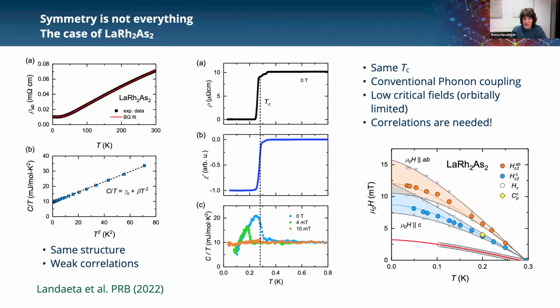What we know from our studies is that the structure is not enough to get the two superconducting phases. So what we did is we studied this sister compound, LaRh2As2. So it has no f electrons and is a weakly correlated material. So the gamma is only 10 millijoule per mole Kelvin squared. And luckily, it's also a superconductor with a very similar Tc of also roughly 0.3 Kelvin. You see specific heat, AC susceptibility, and resistivity. But the upper critical fields are very low. So here, this is millitesla and not Tesla. And they are purely orbitally limited.